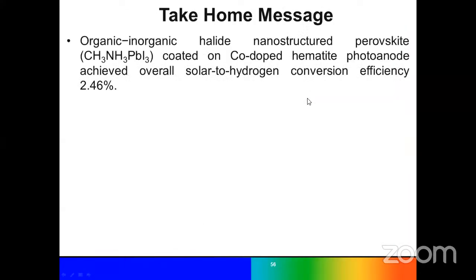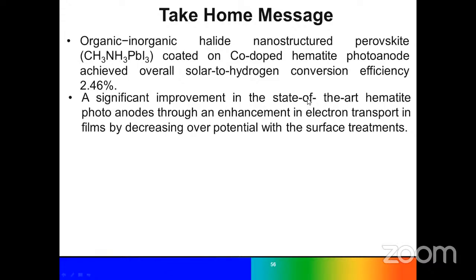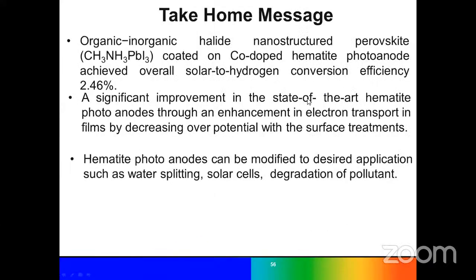Like organic halide nanostructures coated on the photoanode. Overall efficiency we reach is 2.46%, which should be higher for the commercialization of these devices. A significant improvement over the state of the art is the hematite photoanode, with enhanced transport in the film by decreasing the overpotential through surface treatment. Also, the degradation is much lower; it is much more stable compared to the literature.